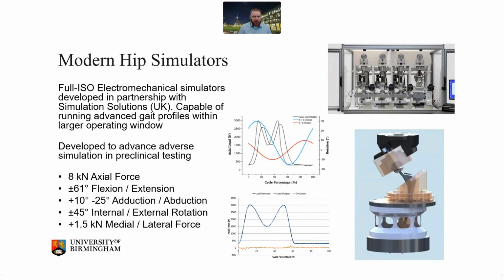But with the fully electromechanical control, we can get a very close agreement to the input profile, and that enables us to do a lot of cool stuff around putting in specific patient profiles. So we developed this advanced simulating platform. We actually went through two. We have a standard plus wear simulator with 3 stations, and then the load soak station for correcting the absorption during wear rates. And this is capable of applying up to 8 kilonewtons of axial force, 60 degrees of flexion extension, abduction, adduction, and also applying medial lateral force, which becomes important when you start looking at the actual force vectors that are involved in joint contact forces.